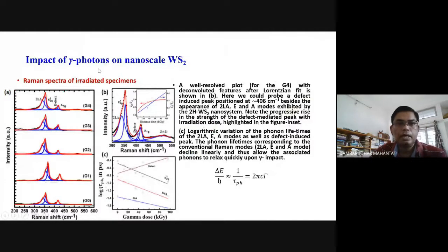Now, impact of gamma photons on nanoscale WS2. So these are Raman spectra. The first one is called the E2G1 mode, which is an in-plane mode. The second one is the A1G mode. You also have the second overtone of the LA mode, longitudinal acoustic mode, what people have reported, and that is just close to the in-plane mode, the 2LA mode. So there is a manifestation of these modes, and mode intensity that we have measured